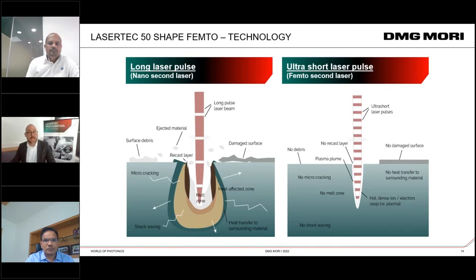You probably have heard about nanosecond lasers. We just heard in the initial presentation about laser cutting and laser welding. This is where usually nanosecond lasers are in use. And for welding, of course, you need to have the heat. You need to have the power in the workpiece to melt the material. But sometimes this melting zone is not what you want whenever you would like to treat a surface, for example. And this is where we talk about the femtosecond laser. The femtosecond lasers have a wavelength which is still the same, but the pulses are much, much shorter. So the material doesn't have the chance to heat up. And if the material cannot heat up, the big benefit is that you don't generate micro cracks, heat affected zones, and so on.